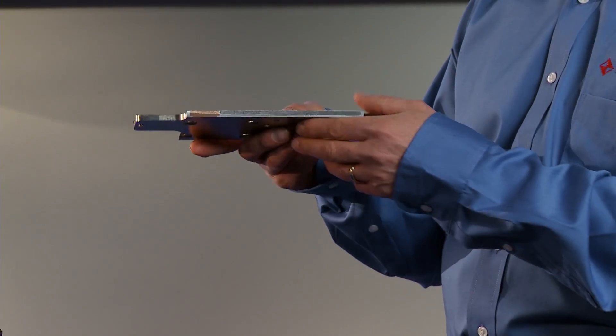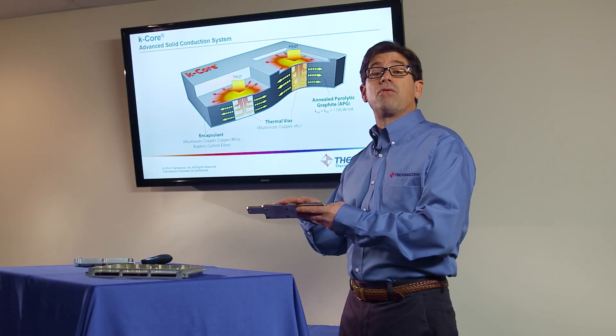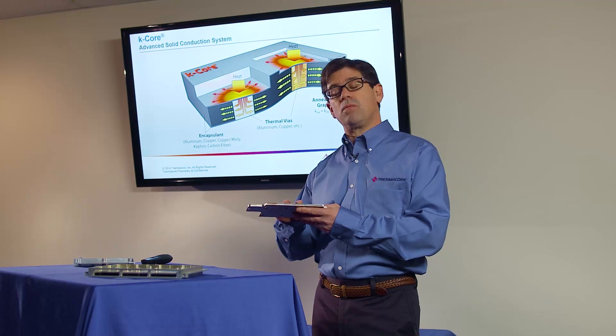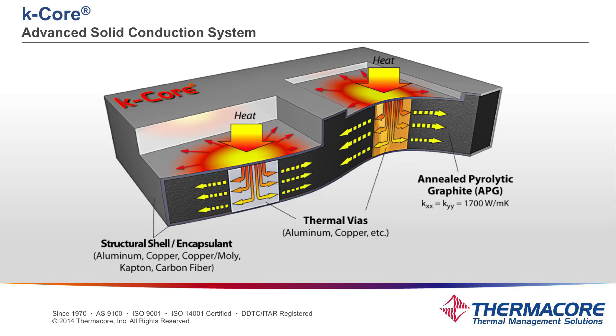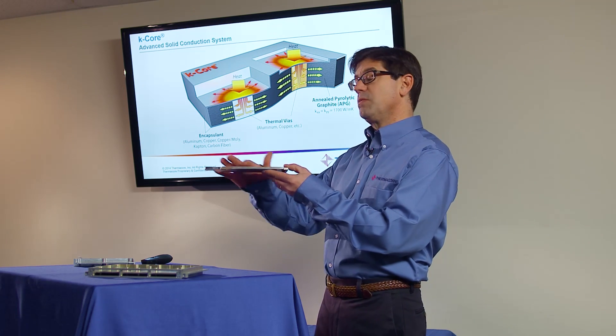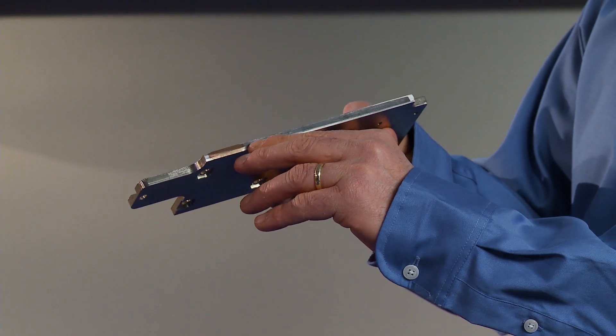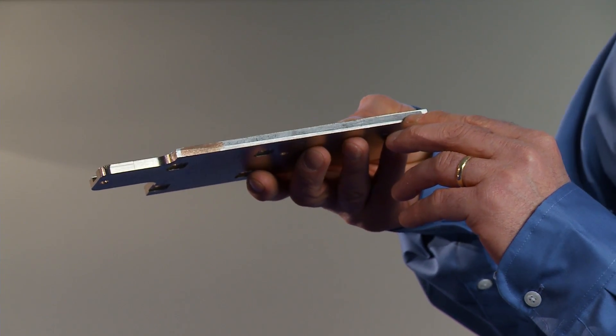Very, very highly conductive in the plane. The annealed pyrolytic graphite has poor mechanical properties, so to satisfy the needs of aerospace and packaging requirements, we wrap a structural shell around it to provide the integrity. The combination of the structural shell with the highly conductive graphite insert results in a composite with very high conductance. In this example, we have an aluminum shell wrapping an annealed pyrolytic graphite core.